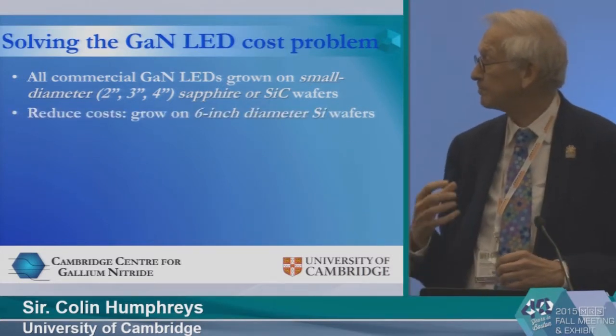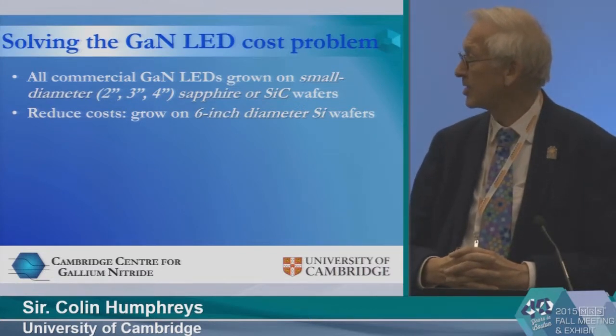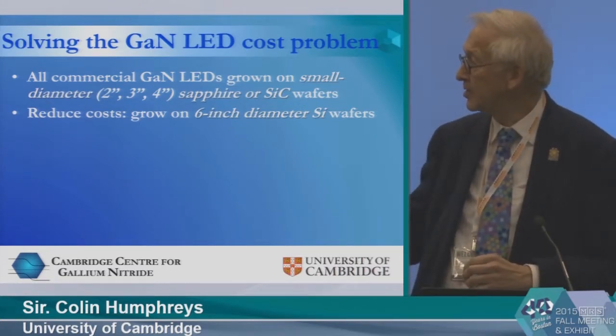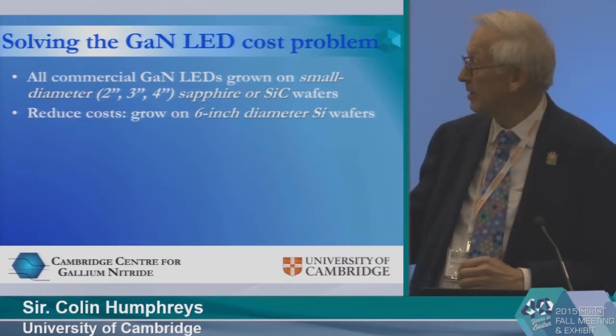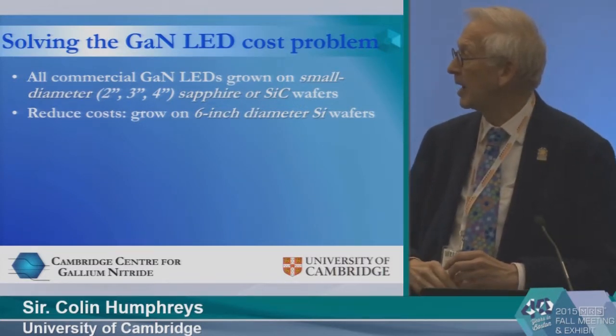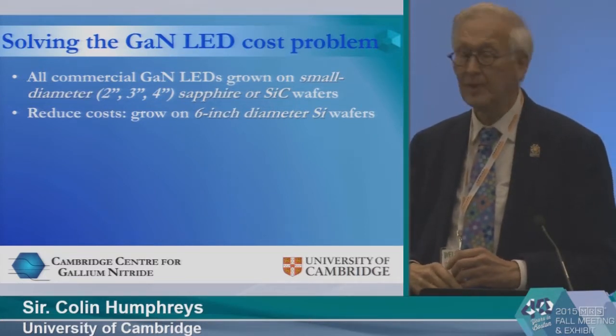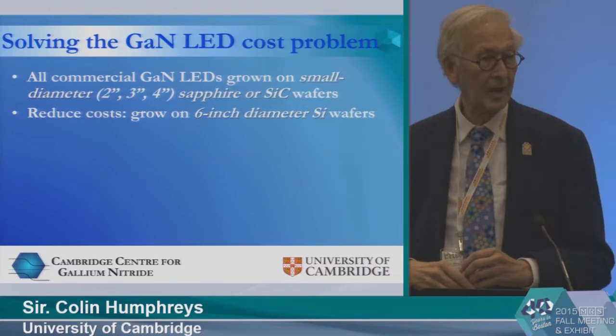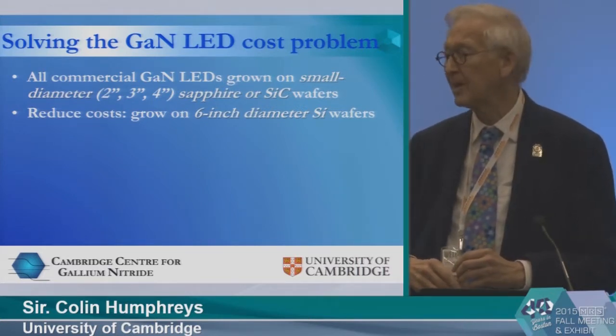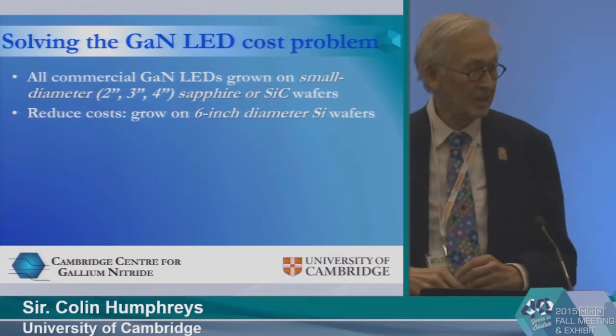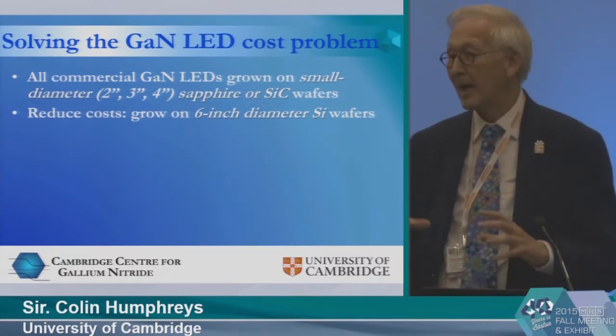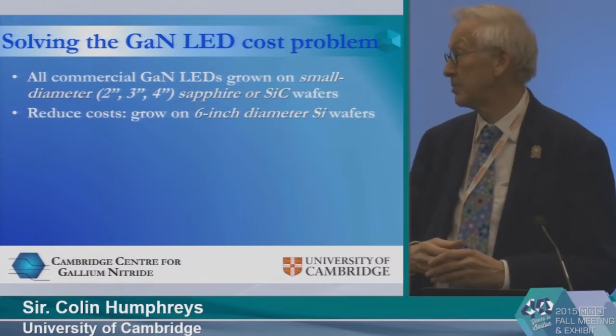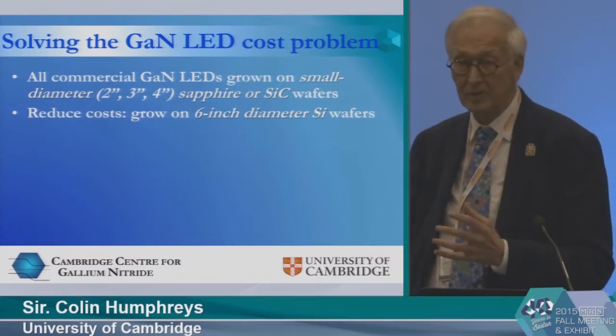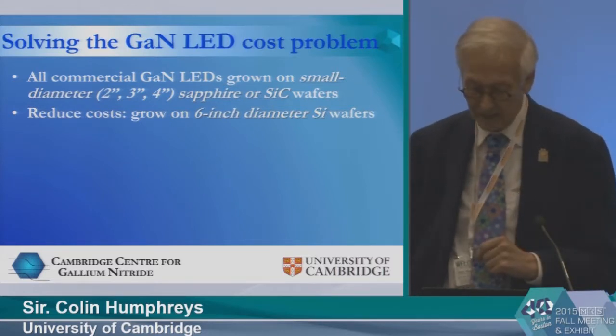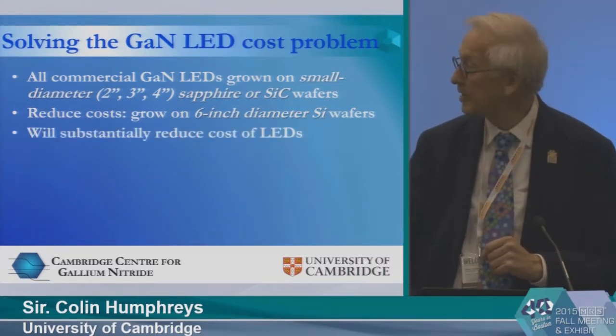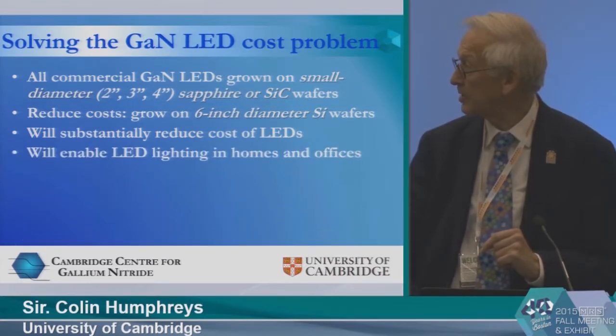To reduce costs, one thing we've been pursuing is to grow on 6-inch diameter silicon wafers. You can instantly see that should reduce costs, because silicon is cheaper than sapphire or silicon carbide. Also, if you grow on a 6-inch diameter wafer, the processing costs of that wafer are not very much more than growing on a 2-inch diameter wafer. On a 6-inch diameter wafer, you get 9 times as many devices as you do on a 2-inch wafer, and because the edge effects are less, you actually get 10 times as many usable devices. So you can see where these cost reductions come in, on growing on a large diameter wafer and also on growing on silicon.